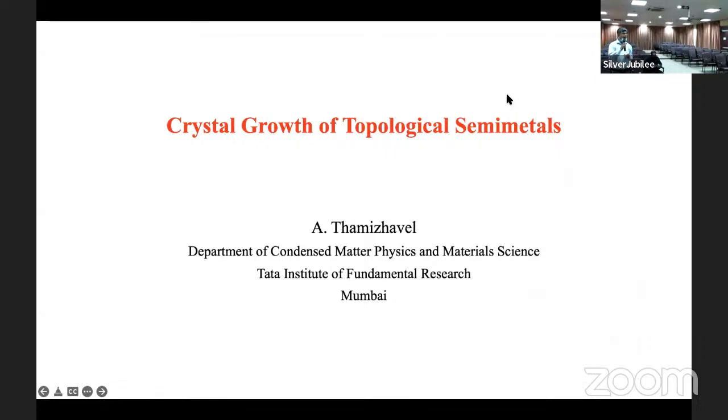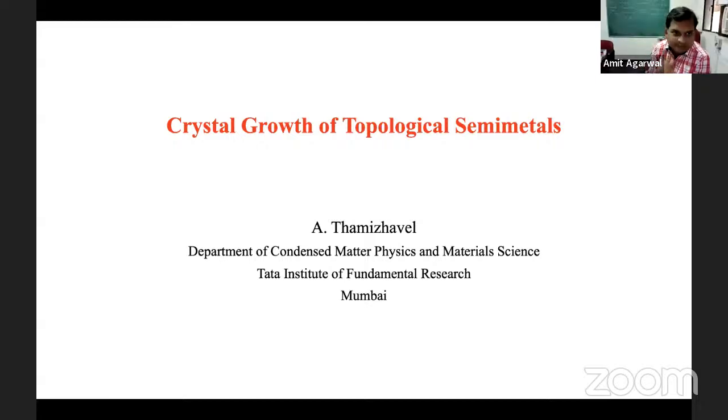So I was curious about this dipole, Berry curvature dipole, these bulk systems. WTe2 you mentioned, right? What is special? So what you need, essential ingredients are number one, inversion symmetry breaking or time reversal symmetry breaking. Either of these two. And asymmetry in the band structure. Meaning it should not be circularly symmetric, or C3 rotation, some asymmetry. Very difficult to specify, but some asymmetry. So some mirror symmetry specifically needs to be broken.